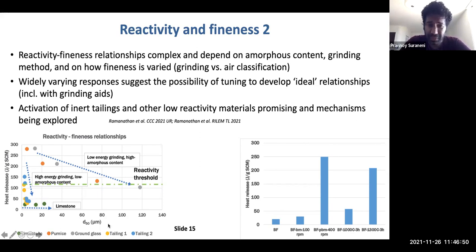The heat release versus D50 is a straight line. On the other hand, if you take highly amorphous materials, for example, pumice and ground glass, for these materials, we find a very shallow relationship between the fineness and the reactivity. These were subject to low energy grinding. I don't know what happens if you put them in high energy grinding. We haven't done that yet. But in low energy ball mill grinding, we find that as the fineness reduces, the reactivity does tail off, but it doesn't drop like this. It drops in a very shallow manner.